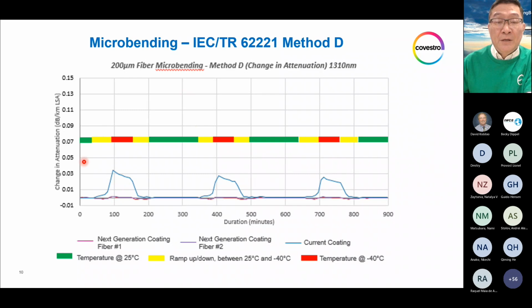I'm giving you one of the actual microbending test results of the next generation coating versus the current coating. Specifically, the coating was applied on a 200 micron fiber. Remember, that's a 125 micron glass cladding size and a 200 micron overall coated optical fiber diameter. So let's look at the details of the test.